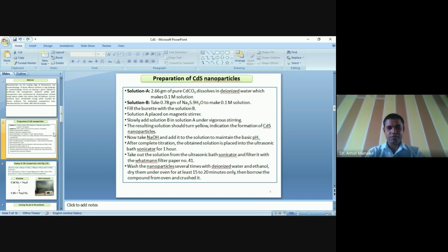After dropwise mixing, we maintain two pH conditions, one acidic pH and one basic pH. We got results from both media, the acidic medium as well as the basic medium. After addition, we placed the beaker into the ultrasonic bath sonicator for 1 hour. Then the cadmium sulfide fine nanoparticles are formed. Then we filter them. The nanoparticles are filtered using Whatman filter paper number 41.